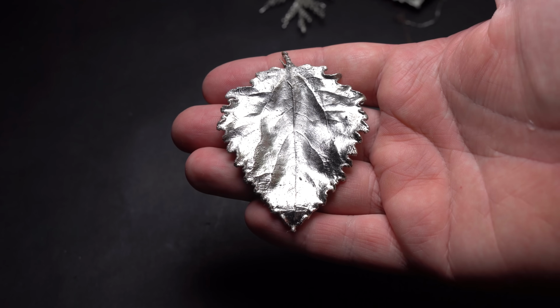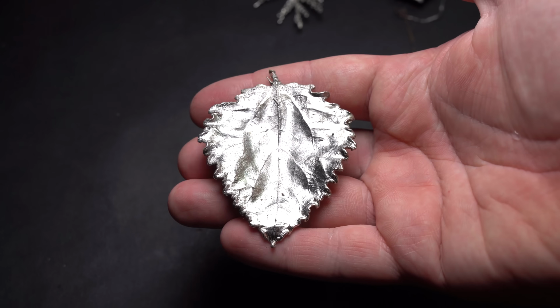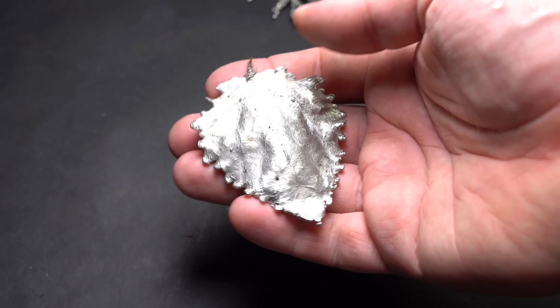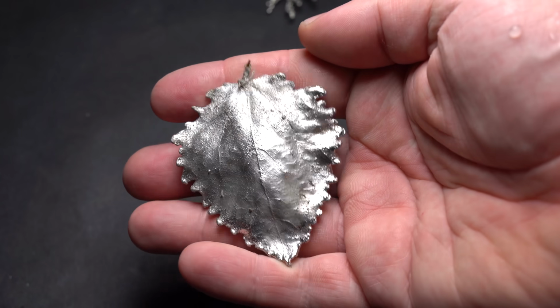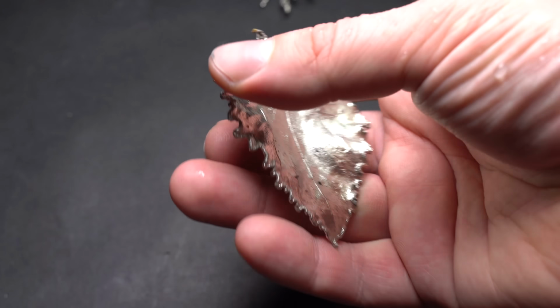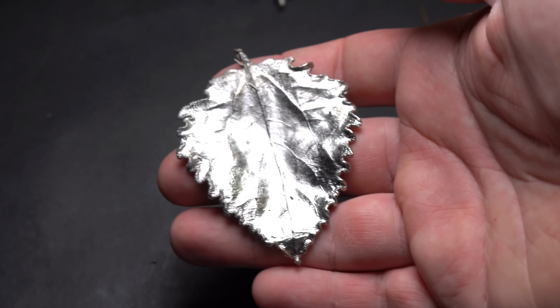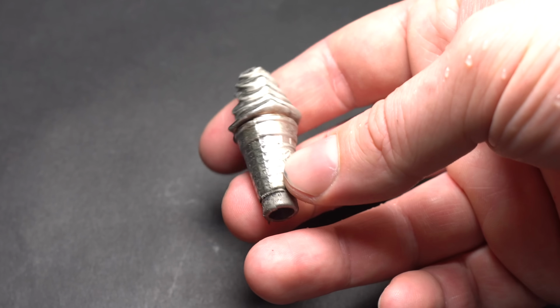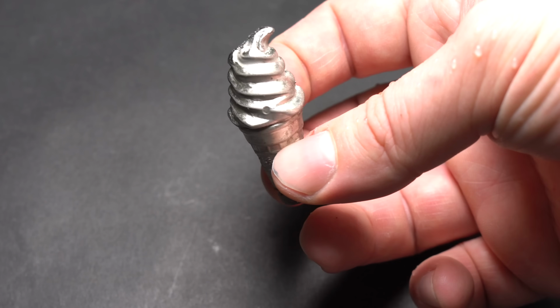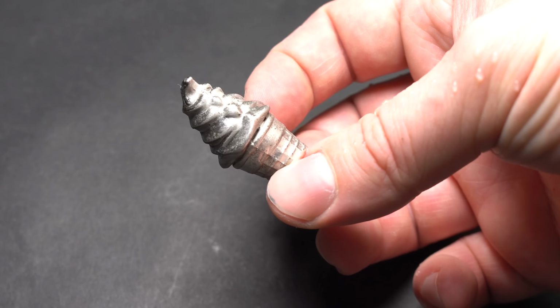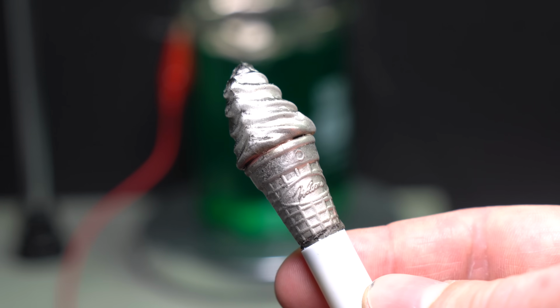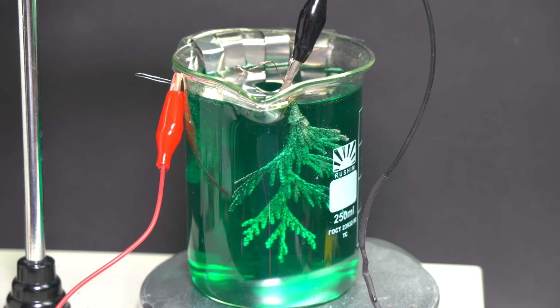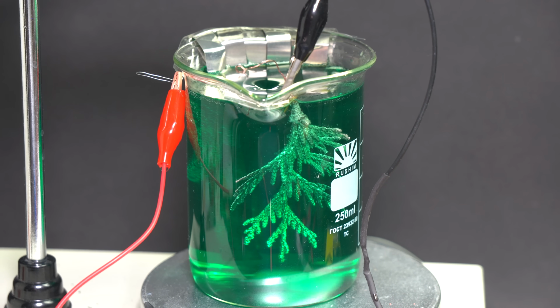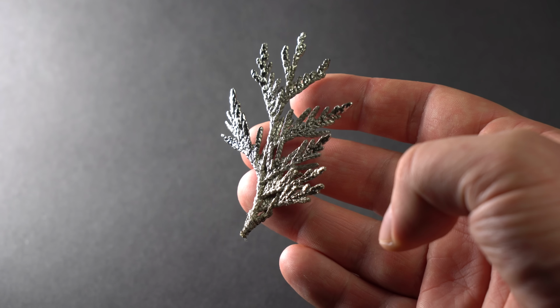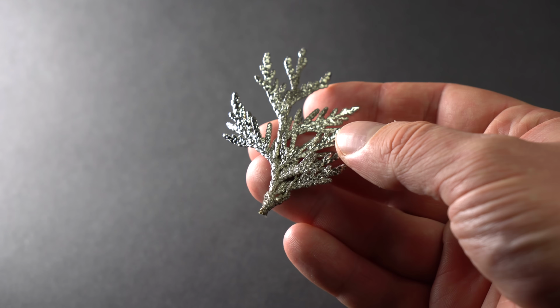Why nearly perfect? Because in the beginning current wasn't strong enough, which is why there formed such bumps on the leaf. That is why you need to keep constant watch on the solution during brightening, and as soon as the solution starts turbiding, immediately increase current by 2 times and observe the result. Besides aspen leaves, I also copper plated, brightened and nickel plated a thuja twig.